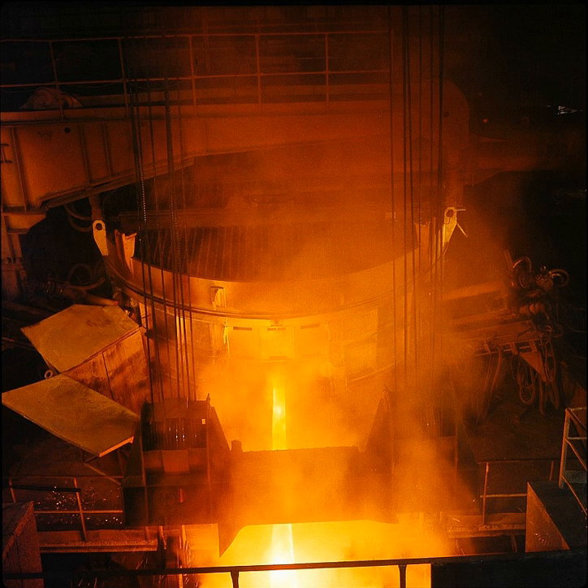A foaming slag is maintained throughout, and often overflows the furnace to pour out of the slag door into the slag pit. Temperature sampling and chemical sampling take place via automatic lancers. Oxygen and carbon can be automatically measured via special probes that dip into the steel, but for all other elements, a chill sample, a small, solidified sample of the steel, is analyzed on an arc emission spectrometer.